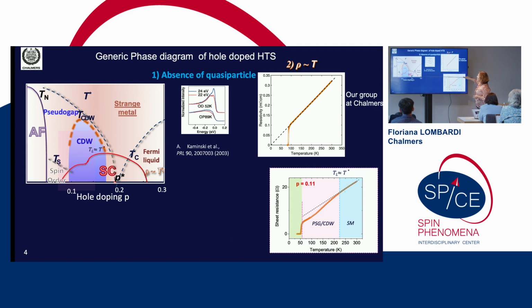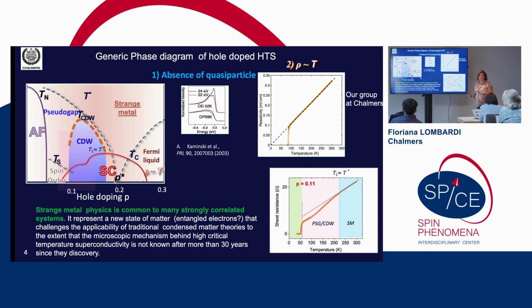However, as I said, this happens in the strange metal phase. So above this P star, when you increase the doping, you recover the conventional Fermi liquid. So you have Fermi liquid, strange metal, and here this is what is called pseudo-gap metal. And what happens to the resistivity versus T, you have linearity here, like you get at higher doping, and then you have deviation from linearity. What breaks this strange metal phase was up to a couple of years ago still a question. This strange metal, as we've heard, is not peculiar only to HTC cuprates, but there are heavy fermions, there is magic angle graphene. So it is something that comes out in strongly correlated materials.